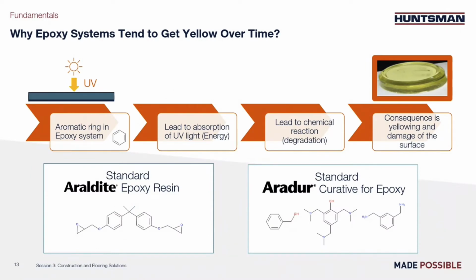So now let's look at the final cured material. Once the epoxy is cured, you get a surface which is subject to UV light. It is clearly more pronounced outdoors, but indoors it's also possible as we generally have windows around us. The aromatic ring, which is the small hexagon represented, absorbs UV light at 254 nanometers. This light is energy, which is dissipated in the material and leads to some degradation. In effect, it results in yellowing and, to an extreme, damage of the surface.